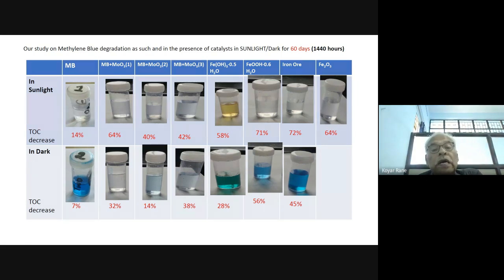Same way, when I use the iron-based catalyst, you can see that the methylene blue color has changed to something yellowish. It is due to the iron present in that one, and we see that around 58% of the organic matter is removed. Whereas another preparation of the iron removes around 71%. It means even in the iron catalyst, if you tailor the metal oxide properly, you can make a lot of difference in degrading any organic matter for that matter.